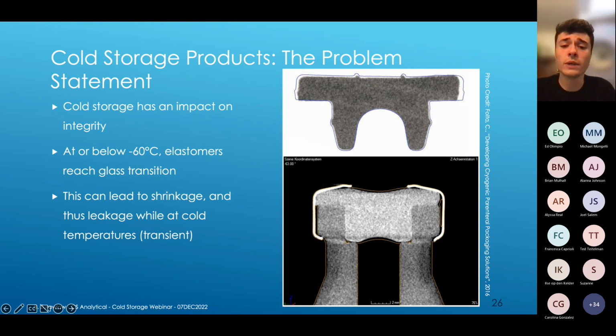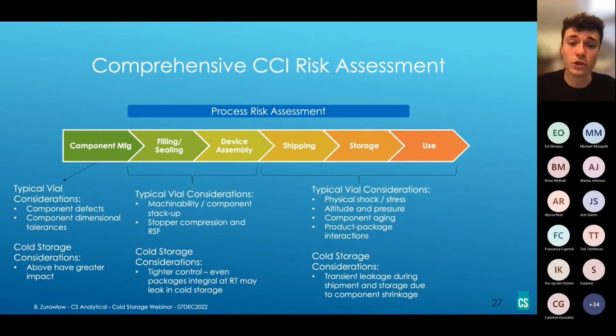And so what this can lead to is leakage through small pathways that are present while we're at ultra cold conditions, but that when we take them back up to room temperature, which is where most traditional CCI measurements are taken, that elastomer has the chance to warm up, reflow, regain its viscoelastic properties, and then reseal. And so what this yields is what we refer to as transient leakage. Leakage that occurs, but it's not a permanent leak. It's not a physical defect in that package system like a crack, a pinhole, or some fibers or debris that cause a channel. This is a transient leak. It can come and go based on the conditions that the package system finds itself in. In this case, of course, that's temperature.